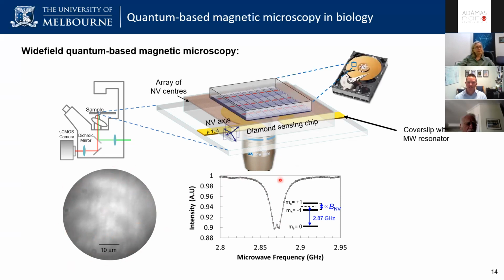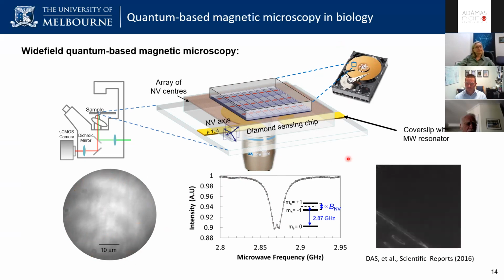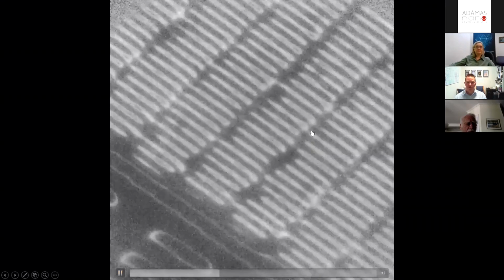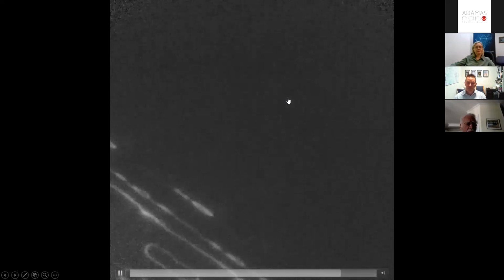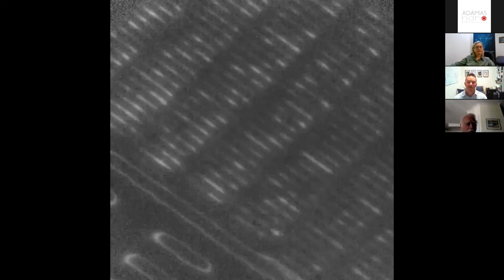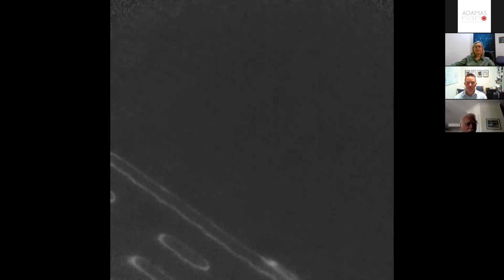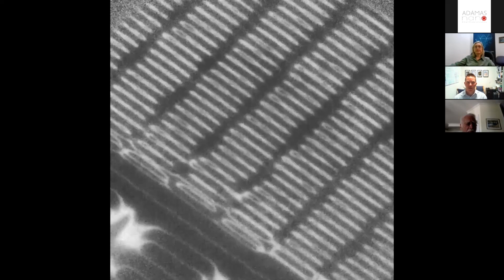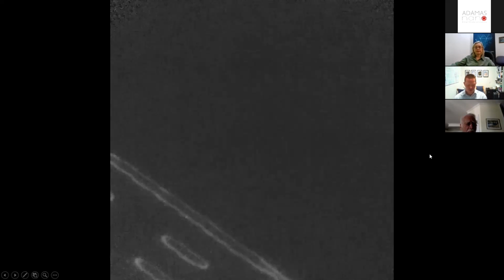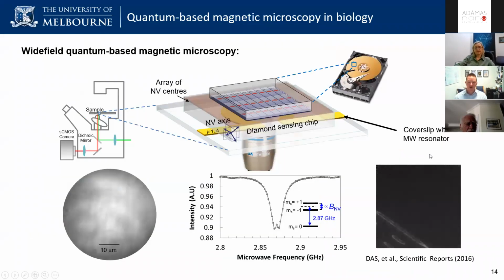And so then if you think about adding some interesting samples, we started off a few years ago by cutting out a magnetic hard drive, putting that down on top of this surface, and then you get these really nice images that you can build up of the magnetic field lines from the magnetic bits on that hard drive. So as the NVs come into resonance with the field from the magnetic bits, you can see these beautiful images as we go. So we have this really nice microscope to now start to image magnetic properties of samples that we put on top.